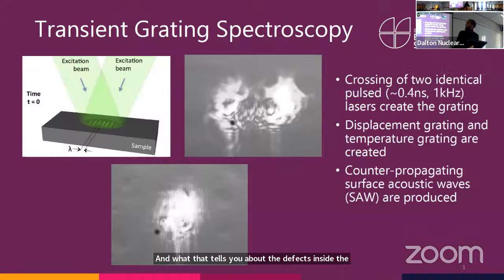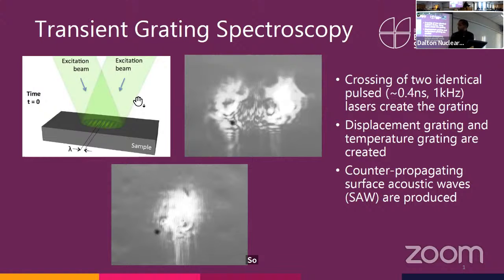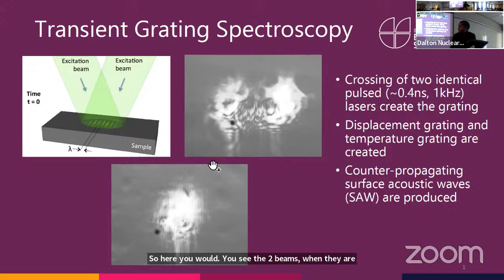So transient grating spectroscopy, as the name would imply, involves a transient grating, which you create using two laser pulses crossed at a sample. So here you see the two beams when they are meeting, and when I properly align it, they create these regions of high intensity and low intensity, and the high intensity regions then heat up the sample in this spatially periodic manner, which gives you a thermal grating of hot and cold, as well as the hot regions expanding outwards, which gives you regions of surface displacement. So you create a diffraction grating on your sample, and this grating is created by pulsed lasers.